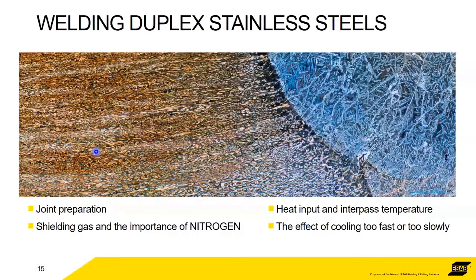Under the microscope, if you see here, this is the base metal. It's a fantastic cross section. You've got nice fine grains. We're going to the heat affected zone, and then the weld. In the weld, you've still got a very nice mixture, it looks to be a good proportion, 50-50 austenite ferrite, but the grains are bigger. This has been made molten and it's resolidified. However, it's been done very well, and you've still got a nice mixture. It's still a duplex structure.